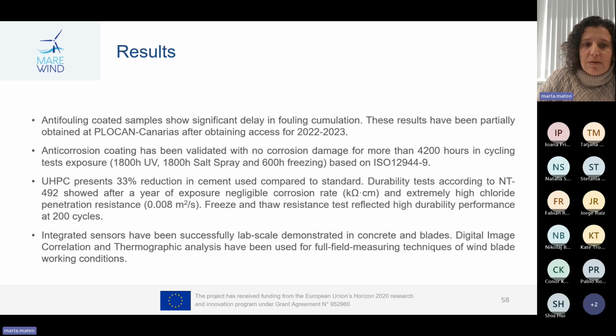Anti-corrosion coatings have been validated with no corrosion damage for more than 4,200 hours in cycling test exposure, as you can see in the slide, with hours of UV exposure, the salt spray, and the freezing based on the issue mentioned there.